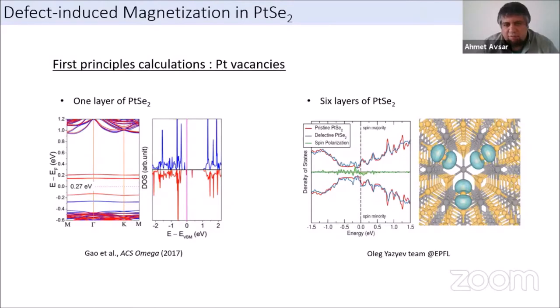And the second result was, as you increase the thickness, the strength of the magnetism was decreasing. Basically for monolayer, it's 6 Bohr magneton per defect, and for 6 layers, they calculate only 1.2 Bohr magneton per defect.